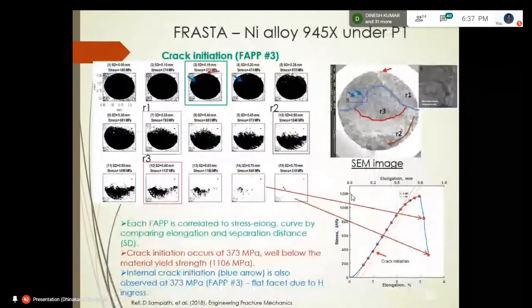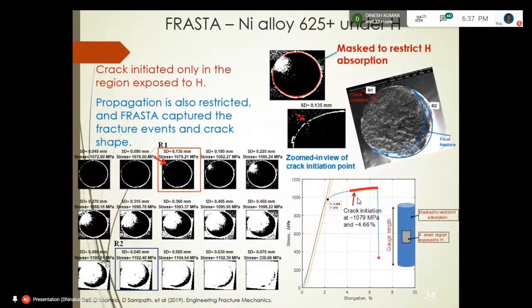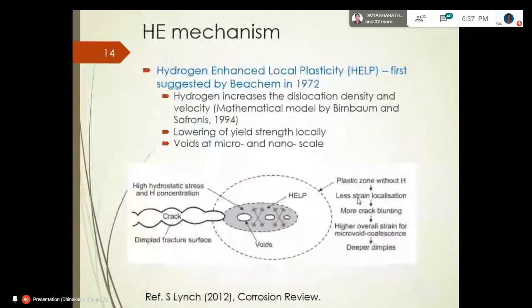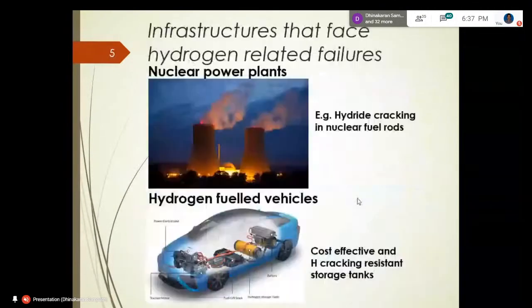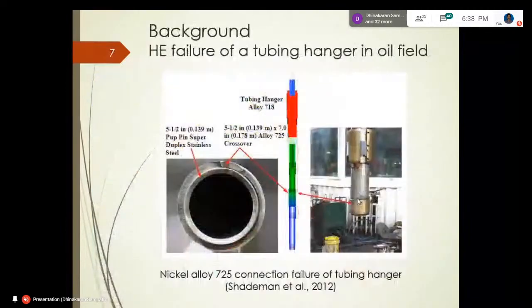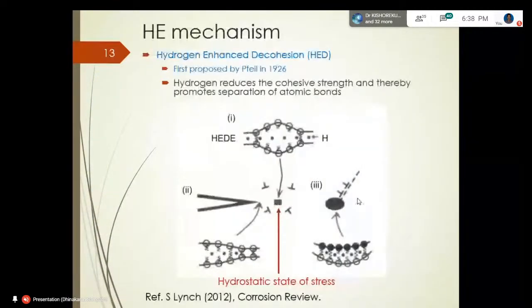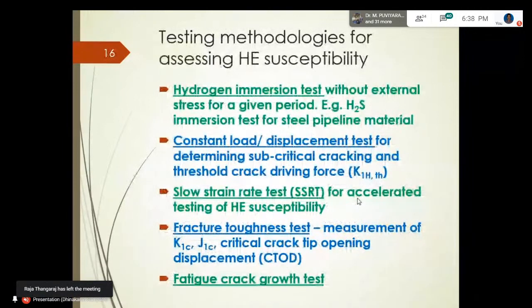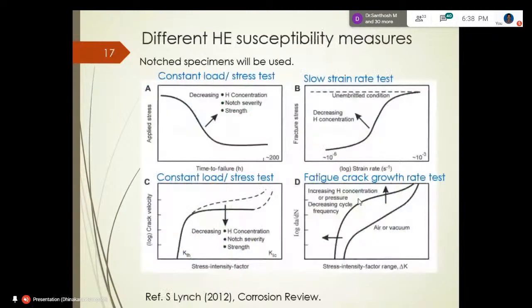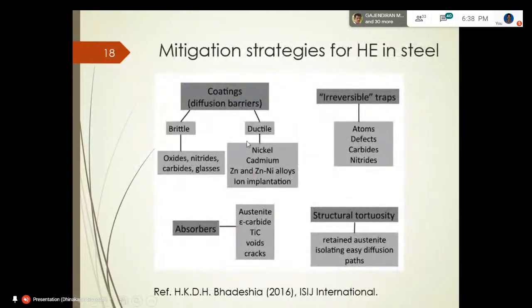Yeah, I think that's again, one should understand the diffusivity of the coating material. Yes, we can use the hydrogen permeation technique or similar technique to measure the diffusivity of the coating. And then, based on which one should decide, and also, how long it has to last, what is the life expected. So based on which one can derive the thickness required. So here you can see that for steel they can go for nickel, cadmium, because these are going to delay the hydrogen diffusion.